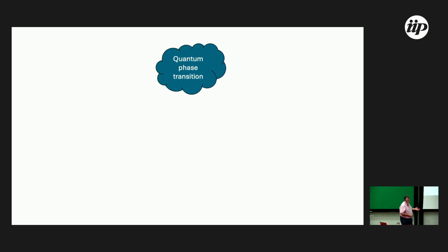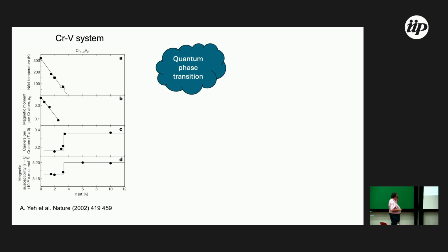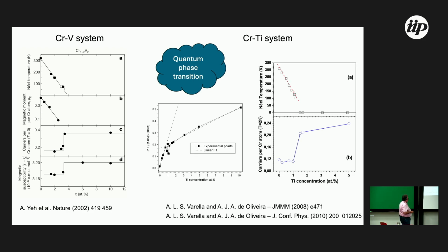Okay. But chromium exhibits a special behavior, quantum phase transition. The quantum phase transition proposed by Yeh in Nature in 2002 is observed in chromium-vanadium: when increasing vanadium concentration, the Néel temperature decreases to 0 K. This is a characteristic of the quantum phase transition. Observing the Néel temperature, the magnetic moment of chromium-vanadium decreases, the carriers show a jump, and the magnetic susceptibility shows a jump as a function of the vanadium concentration. And observe the same behavior in chromium-titanium.